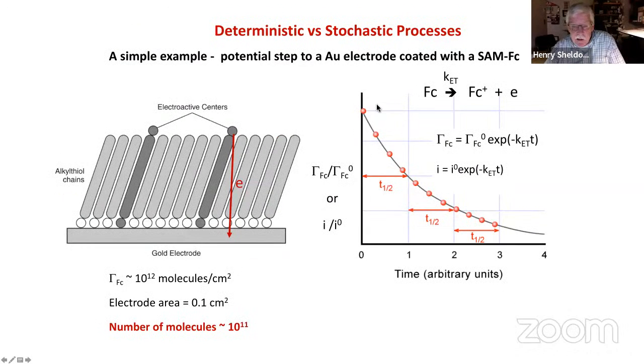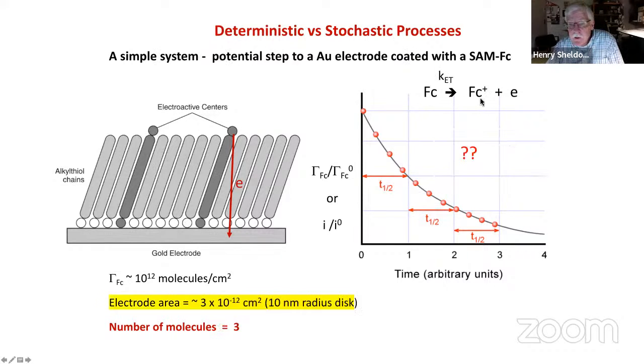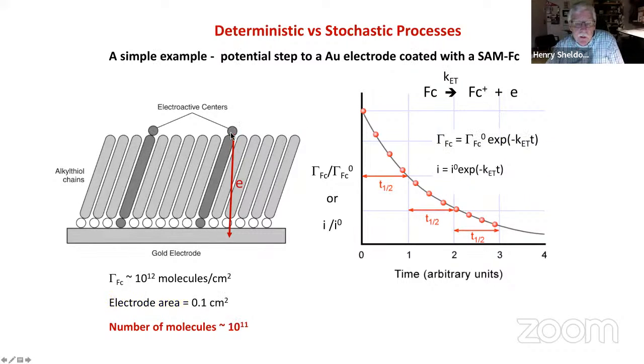Okay, let me just give an example of deterministic versus stochastic processes. This is, I just made this example up. This is a thought experiment. This is the old Chris Chidsey experiment, where you have a gold electrode and you have a self-assembled monolayer of alkyl thiols. And some of the thiols have an electroactive center. This could be a ferrocene center. And the experiment is to apply a potential so that you drive the oxidation of ferrocene to ferrocenium. So electrons are moving from the redox group tethered at the end of the SAM layer, and they're transferred or they tunnel to the gold electrode. And the experiments, when Chris did these experiments, and other people have done them too, the surface coverage of ferrocene is on the order of 10 to the 12th molecules per square centimeter.